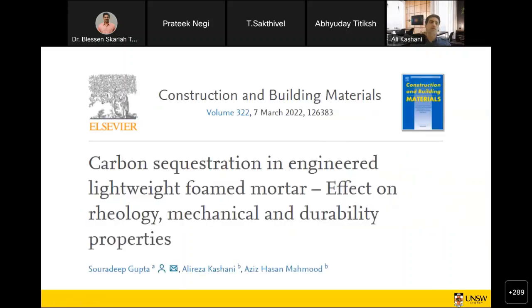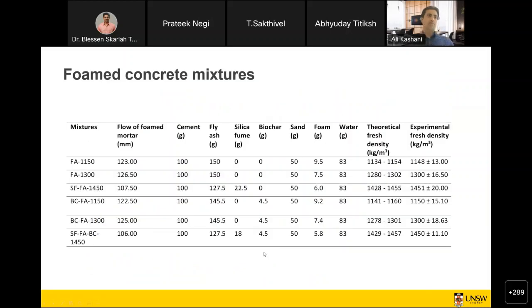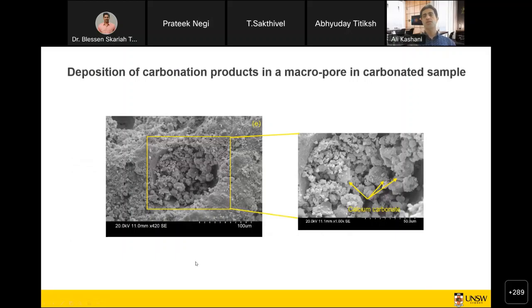Some of the results that I'm showing are the good work of our colleague, Dr. Gupta, when he was at UNSW as a research fellow. And now I think Dr. Gupta is an associate professor at IIT in India. So we looked at foam concrete samples with fly ash, silica fume, and also biochar at different densities, and we introduced them into carbonation. As you can see, the calcium carbonate product easily forms inside the pores of the concrete.